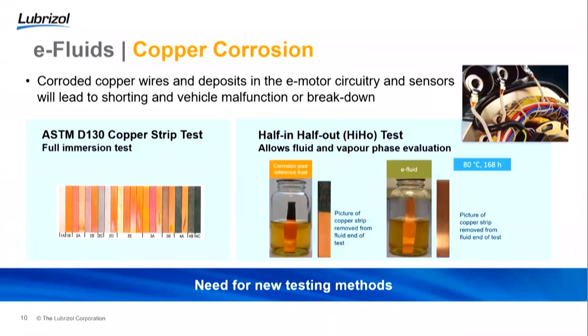And what we found is that standard tests for copper corrosion, like the ASTM D130 copper strip test, are quite subjective tests, and they don't always show what is happening in the vehicle in regards to corrosion. There are developments of the ASTM D130, for example the half-in, half-out test, where you can see pictures here of the coupons immersed in the oil, but we also take care of the vapor phase. You see on the left there that although in the solution phase there's no corrosion, actually in the vapor phase there is corrosion there. So we really saw a need for new testing methods with regards to copper corrosion.